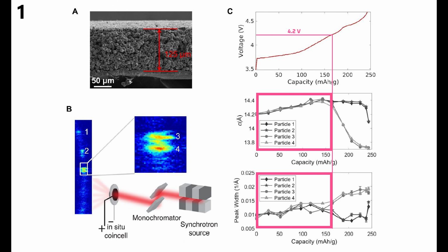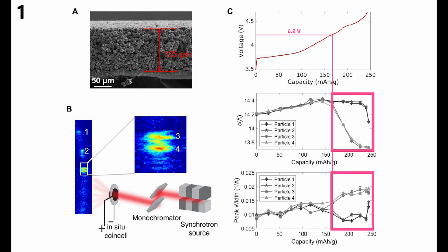Below 4.2 volts, the crystal structures of the particles progress in unison. Then, above 4.2 volts, particles 1 and 2 diverge from particles 3 and 4, showing differences in the crystal structure, indicating differences in lithium content. Differences in lithium content mean the particles are losing lithium at different rates, which means the particles are experiencing different voltages. So what the graphs are showing is that above 4.2 volts, different regions within the broader cathode film are experiencing different voltages, which in turn means different degradation rates.